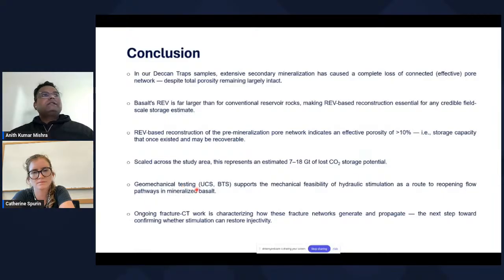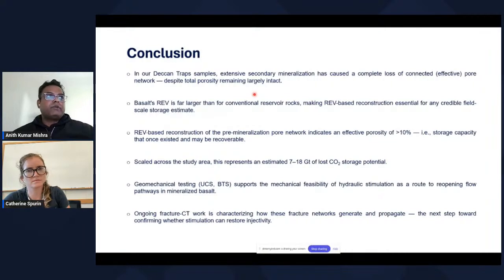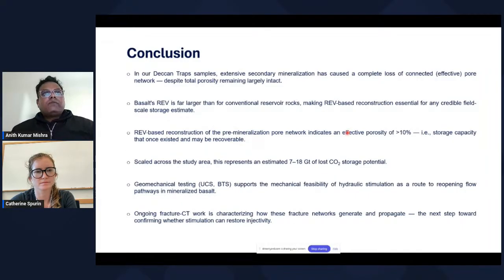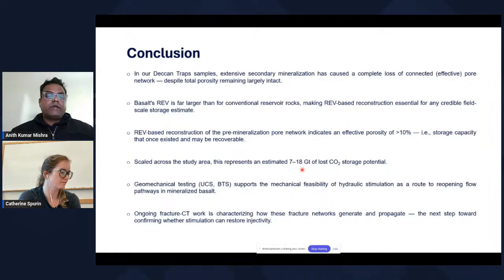So the conclusion of this study is that in our study area, the Deccan trap is extensively mineralized, and there's a complete loss of effective porosity, or connected porosity, at present. The second takeaway is that basalt's REV is much higher than conventional siliciclastic reservoir rocks, and it is very important to construct a baseline for the REV for basalt before coming up with any sort of storage estimation. Within our study area, we also found that at least 10% effective porosity was present in the samples, which is now completely lost. And this loss has resulted in 7 to 18 gigatons of lost CO2 storage potential.